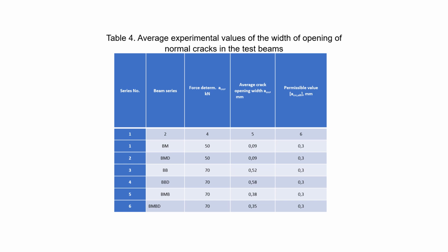The values of the width of the normal crack opening of the experimental beams given in Table 4 indicate that BMD series beams have the same value of normal crack opening width as the control BM series beams, 0.09 mm, and do not exceed the maximum permissible value of 0.3 mm. Beams of the BBD series reinforced with basalt-plastic reinforcement showed a larger value of the width of normal crack opening by 11.5% than the BB series, and exceeded the maximum permissible value by 93%.